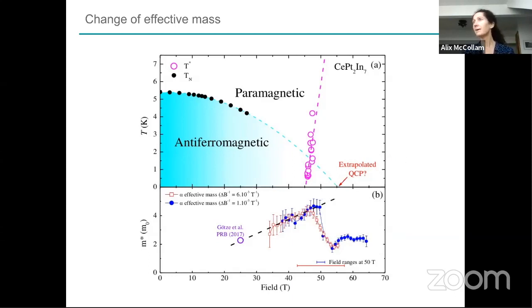So yeah, this is a very good question. Why extrapolate to the quantum critical point? It could be the quantum critical endpoint of the valence transition. Exactly, I agree completely. We made this before we had done these measurements. We measured the heat capacity up to 35 Tesla, and we saw that we were coming down here with the antiferromagnetic transition, and we thought, okay, maybe it's logical to extrapolate this to a quantum critical point. And then we suppose, what type of quantum critical point is this? Is there going to be a Fermi surface transition?